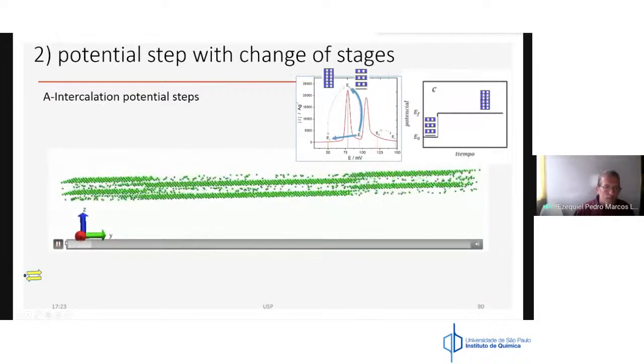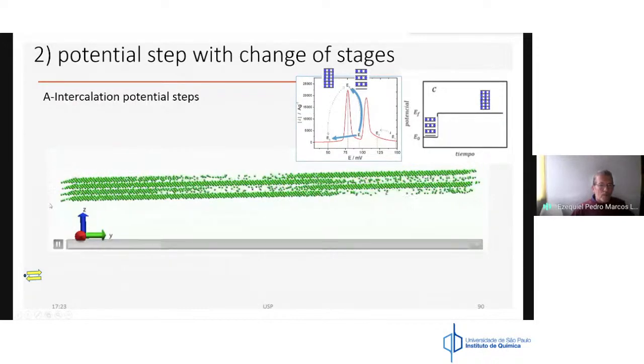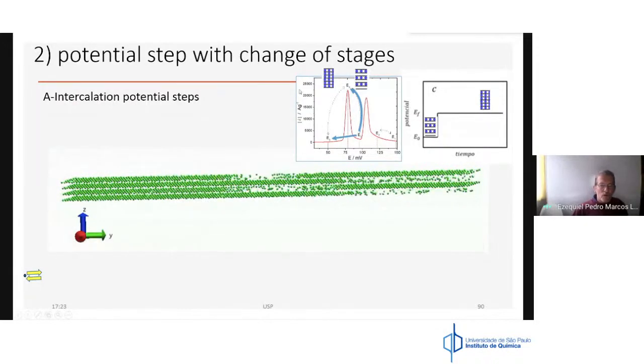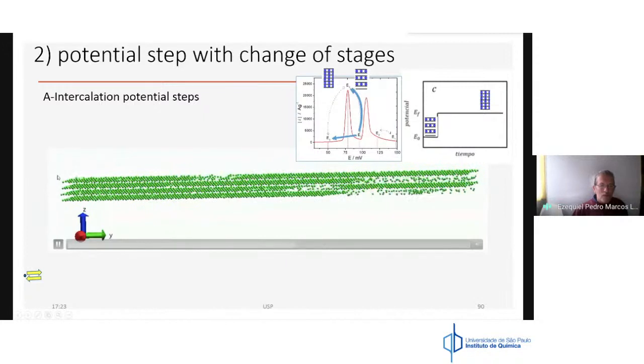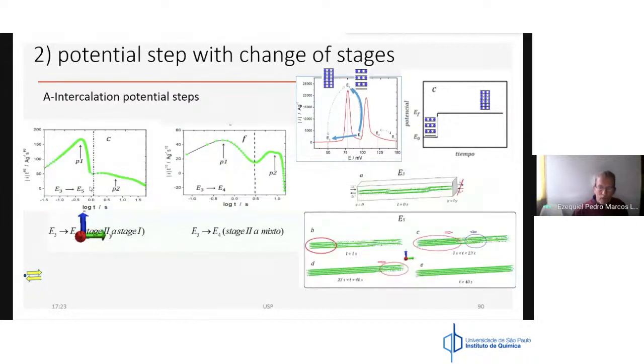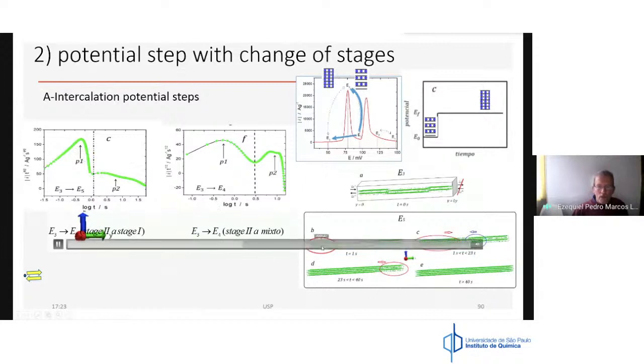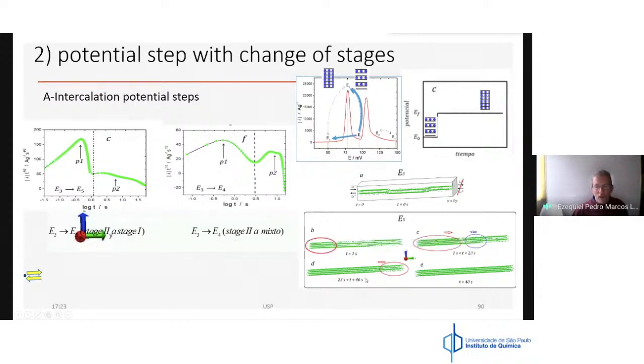Here you can see what happens when you start filling this. When you run from this structure to the other structure, you get a filling here, and if you take a closer look into the detail of the way you fill, you will find that you get this occurrence. This maximum has to do with the cluster. You have the cluster here, and this cluster is responsible for this maximum. We get exactly the same information as the experiment, but the people making the experiment, of course, cannot see what is going on with the system, at least not with the technique they have. And we could find that the origin of these maxima has to do with this cluster.